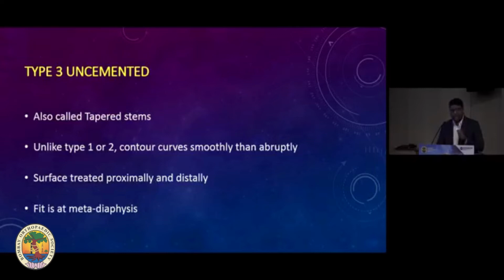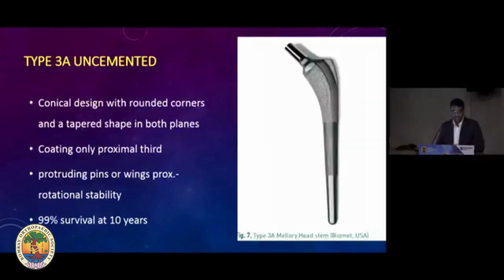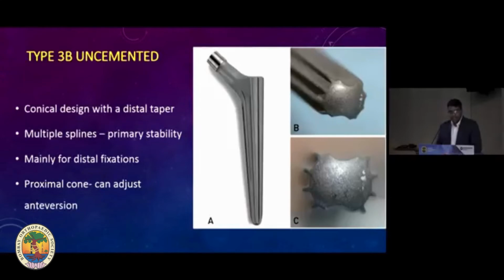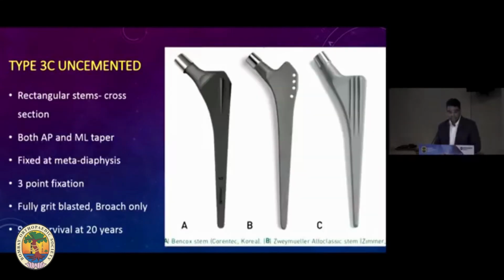Type 3 stems are the tapered stems, very popular these days. Unlike type 1 and 2, they are smoothly curved down rather than abruptly changing their taper. They are surface coated proximally and distally, and they fit at the metadiaphysis. Type 3A is the Mallory-Head stem. It is conically designed with rounded corners. It has proximal wings and fins for better rotational stability, 99% survival at 10 years. 3B are the popular Wagner stems, a conical design with multiple longitudinal splines for better rotational stability. They are mainly used for distal fixation, and you can adjust the version for the same.